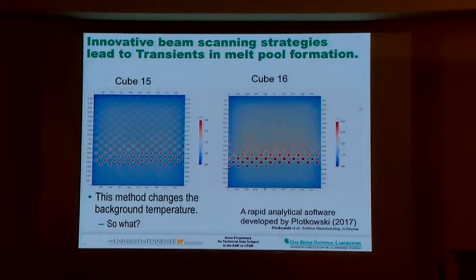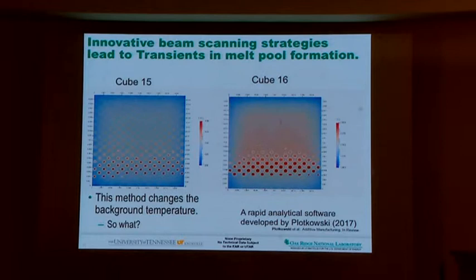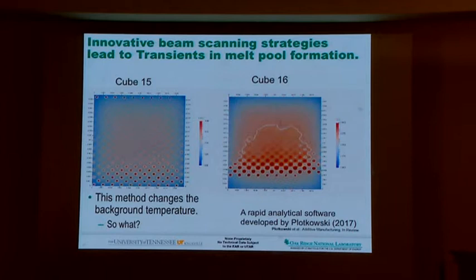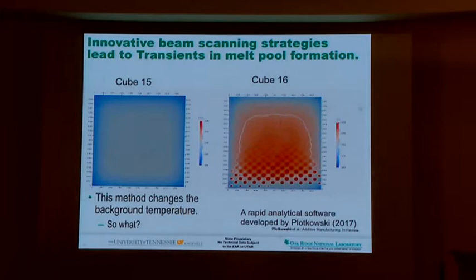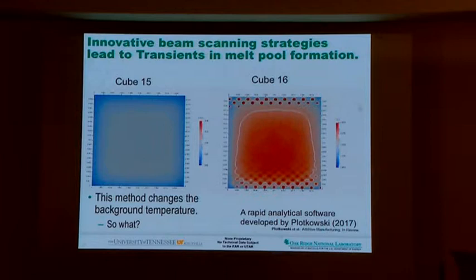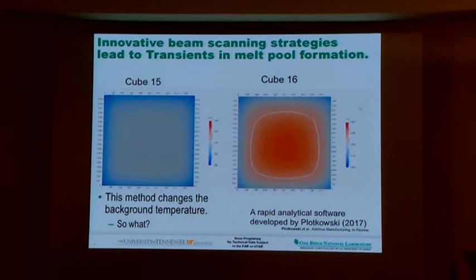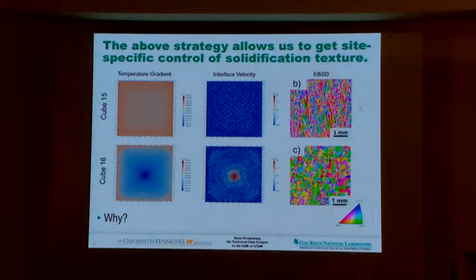What you will see is in the cube 16, each and every individual melt pool will join together and make a big lake of molten pool. So when you have a big lake of molten pool, your alarm bells in your head should go up. That is low thermal gradient, and this is high thermal gradient. So by doing these subtle changes in your melt sequences, you can go from a high thermal gradient to low thermal gradient. Can we get the same thing? Sure. You can actually go from a columnar to equiaxed structure by changing subtle differences in the spot melting pattern.